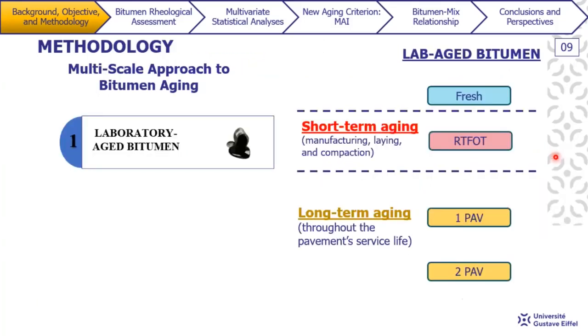So to better understand the aging phenomenon, the methodology that was adopted is what we call the multi-scale approach to bitumen aging. We start off with scale one, that is a laboratory aged bitumen. So here we have our bitumen, and it's short-term aged via RTFOT, that represents the aging that takes place during asphalt mix manufacturing all the way to compaction, which is at high temperatures, temperature superior to 100 degrees Celsius. And this period we also call short term aging. And then this bitumen was further aged via 1 and 2 times PAV that represents the aging that takes place throughout the pavement service life.